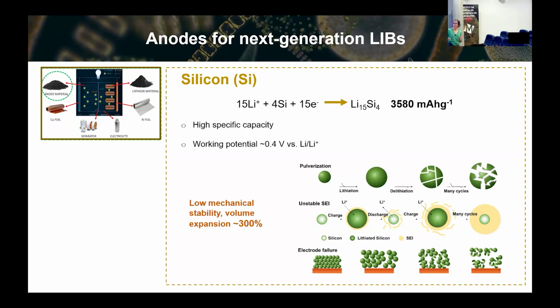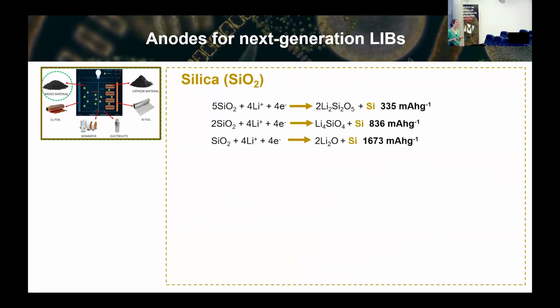And together with silicon, other alternative materials have emerged, and one of them is silica. So silica is quite peculiar, because some years back somebody would say, okay, silica is impossible. It's an insulator. You cannot put silica in a battery. And silica actually reacts with lithium ions with a very specific reaction mechanism, through different reactions in which different silicate phases are formed, and lithium oxide plus silicon. And it acts as an in situ convertible oxide, meaning that these reactions will happen once, and then the silicon that is produced there will reversibly lithiate in further cycling.